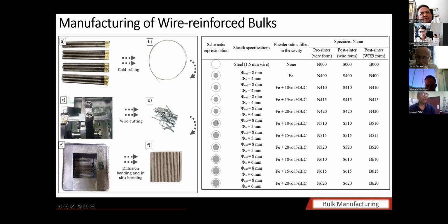Then the core diameter is increased, again 10, 15, 20. And then again the core diameter is increased, and 10, 15, and 20. All these specimens are prepared for seeing the influence of iron boride phases, at the pre-sinter state and also the post-sinter state. B stands for the bulk material, S stands for after the sintering, and N stands for the non-sintered state, before the synthesis of iron boride phases in the wires.